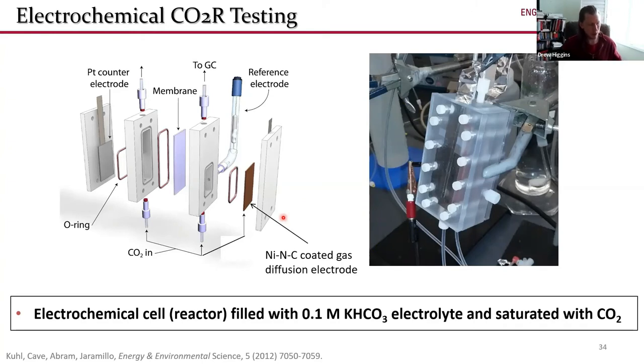Then we wanted to understand what effect the synthesis methods that were used and the properties of the catalyst had on the electrochemical CO2 reduction performance. And so we tested these catalysts in an electrochemical reactor that was home built and essentially looks like this, where we took the catalyst, deposited it onto an electrode, filled the reactor with 0.1 molar potassium bicarbonate, dissolved a bunch of CO2 in there, and started to do electrochemical CO2 reduction measurements.